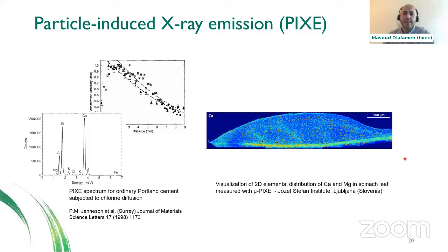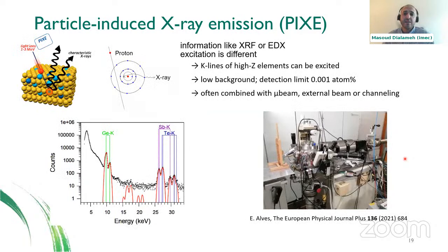PIXE can't detect low-Z elements. How can we make them detectable? Any detector limitation? So maybe a slight correction. PIXE is capable of also detecting the low Z elements like boron or you name it. The limitation is that if you have a substrate, you will have a huge peak of the substrate signal, which can mask the signal of the low Z element.